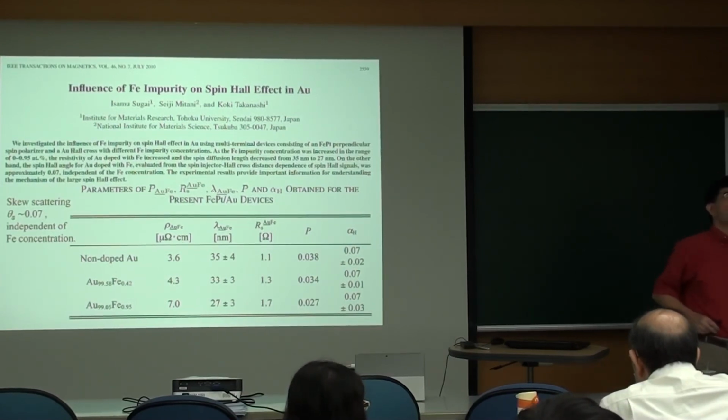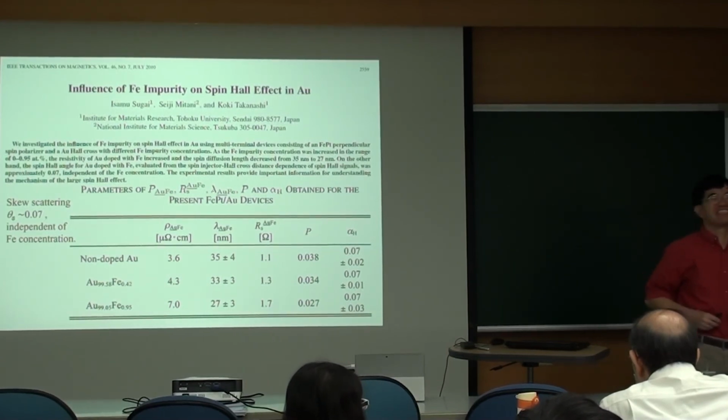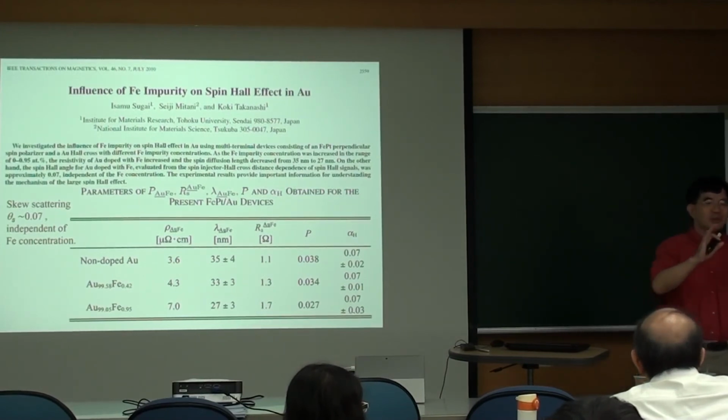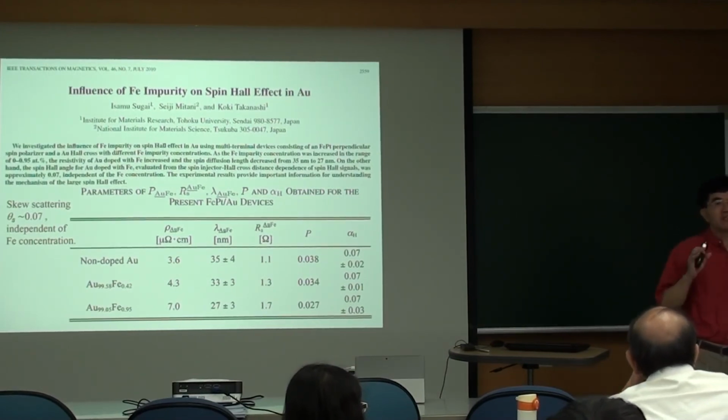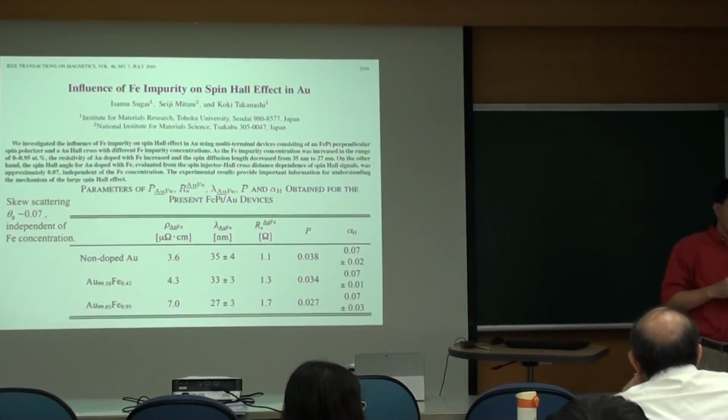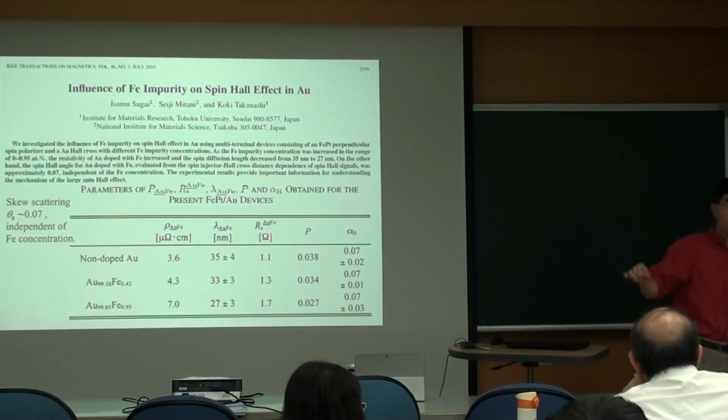Well, I don't know the answer, because that's a question for you, isn't it? Maybe you can make a uniform sample. But basically, we calculate what is in principle a quite robust intrinsic spin Hall conductivity for platinum. That quantity is quite reliable. But the spin Hall angle is different, because you divide this quantity by something else, and that quantity is not controllable when you make the sample.